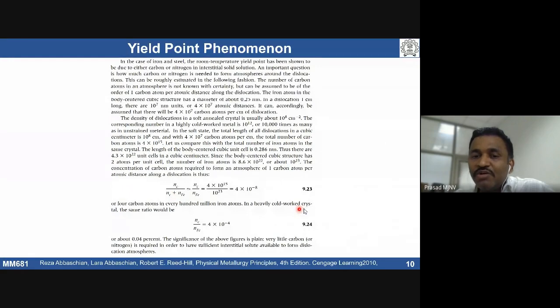In heavily cold worked material, if we take Nc by Nfe, it's about 4 into 10^-4. That means we need only 0.04% of carbon to pin a heavily deformed material having a dislocation density of about 10^12 per centimeter square. That much is good enough to pin the dislocations.